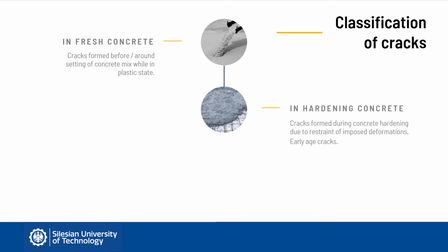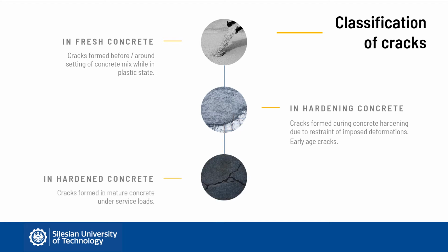Significant cracking can occur during the period of hardening of concrete, which may have significant impact on the structure during its service life. These early age cracks are formed due to the restraint of imposed deformations caused by cement hydration and may reach significant heights, depths, and widths, often exceeding allowable limits. These cracks can grow further in hardened concrete when service loads are superposed on the structure. The most well-known cracking is this observed in mature concrete, which is caused by mechanical loading acting on the structure during its operation, but also other actions such as additional imposed deformations during service life.